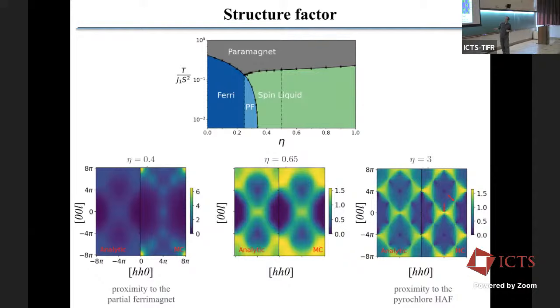And these diffuse dots, this broad scattering, they are where the Bragg peaks of the ferrimagnet were. So they could just correspond to short-range ferrimagnetism. So this region is disordered, but it's disordered in a kind of trivial way, like a short-range ferrimagnet.